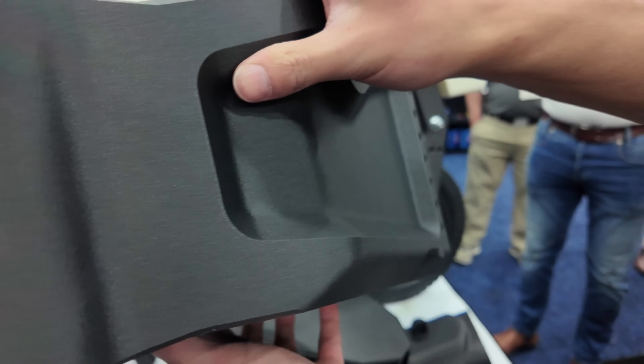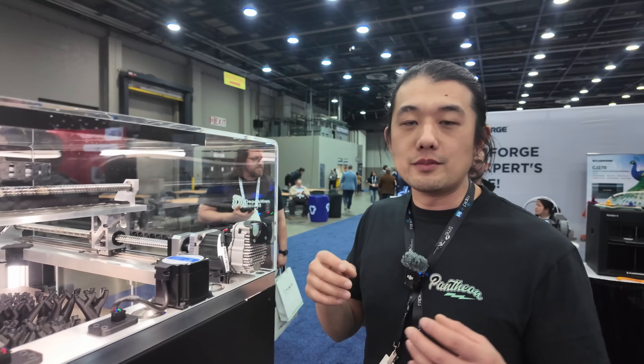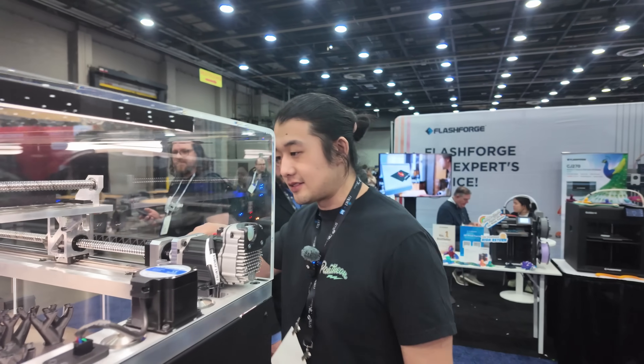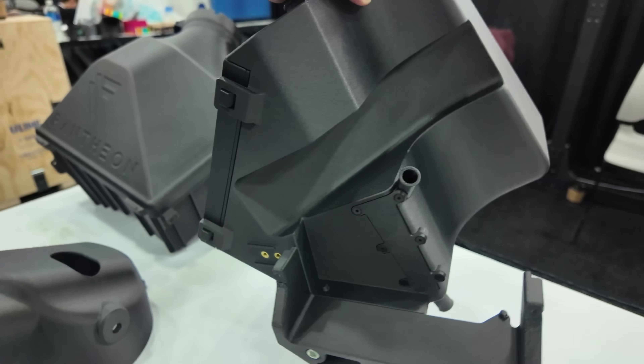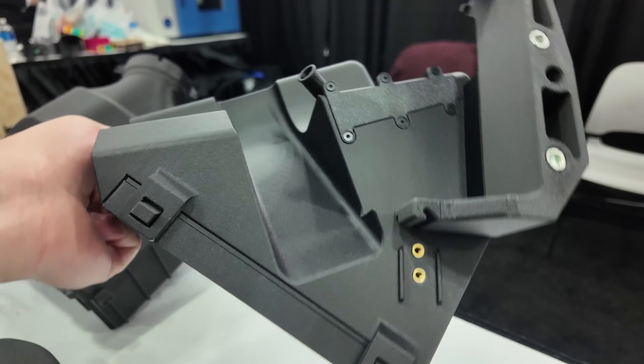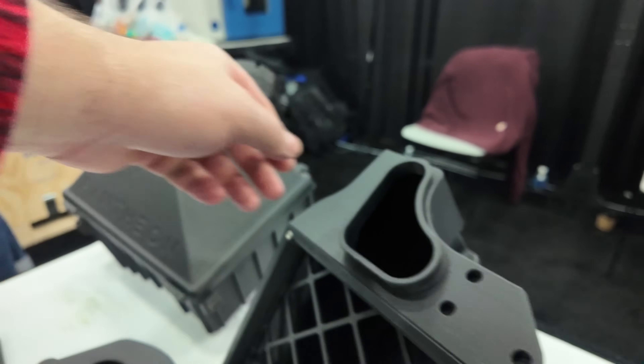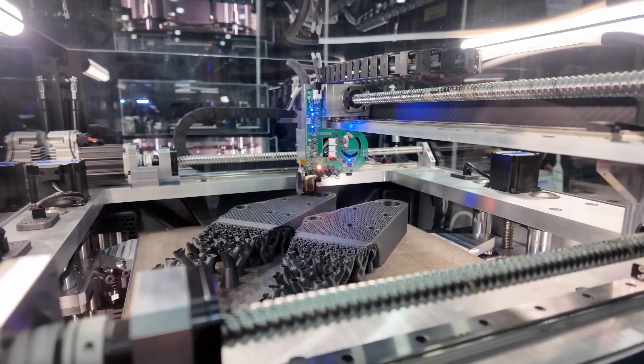The only ways you make bond strength better is more heat or more pressure. More pressure means more dense. But if you go a little bit too much or it's not perfect, you get all these overextrusion errors that look terrible. You can see the sidewalls are pretty much perfect. It is a carbon fiber filament, which is kind of known for making everything look good — but this looks good. We've got a lot of low-level feedback from our TMC drivers now, using that to measure extrusion force. We built a model to infer it, so we know how hard we're pushing. We're looking at our load cell a lot more in real time, so we've built more of a closed-loop model.